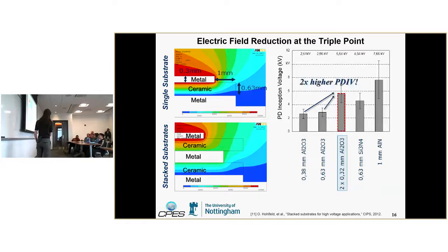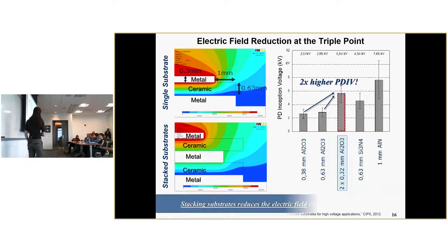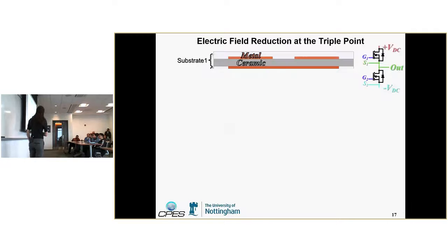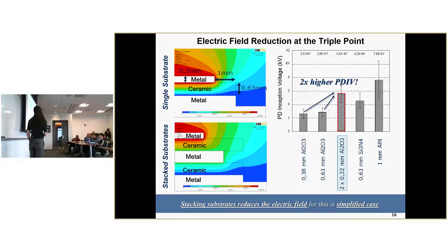And you can see that actually when you have two stacked ceramic substrates, you get 2 times higher partial discharge inception voltage. So what that means is that instead of seeing partial discharge at 3 kV, you're now seeing it closer to 6 kV, which is a significant increase. Okay. But this was kind of an oversimplified case.